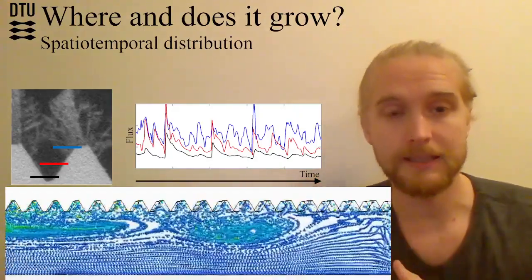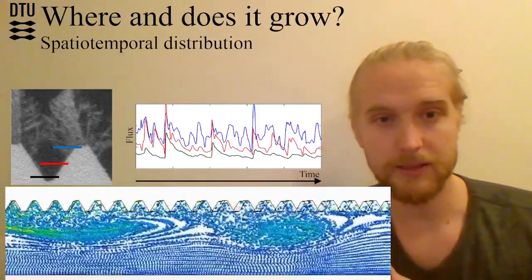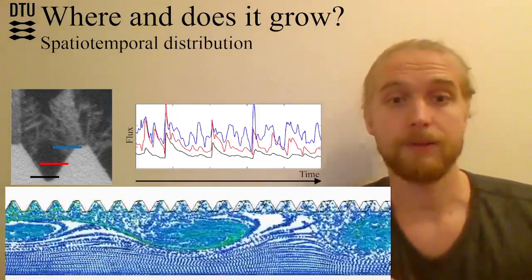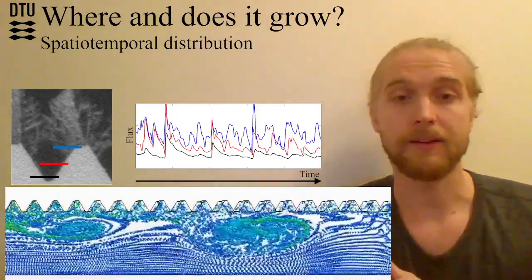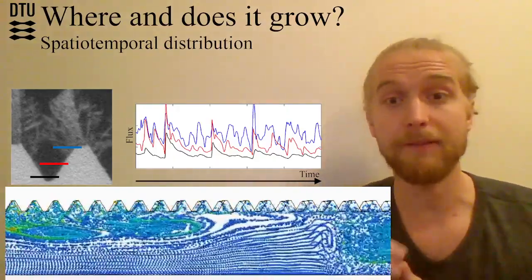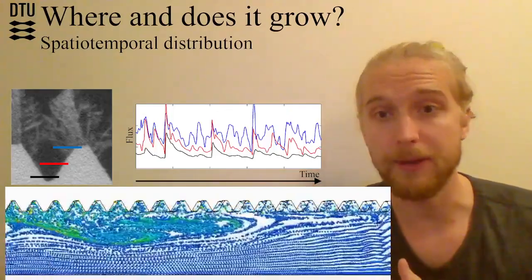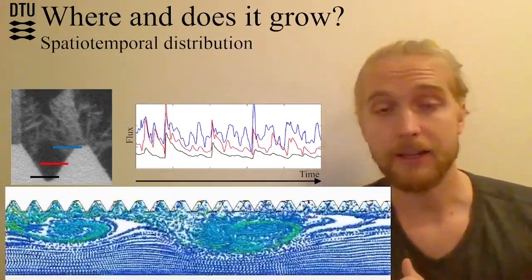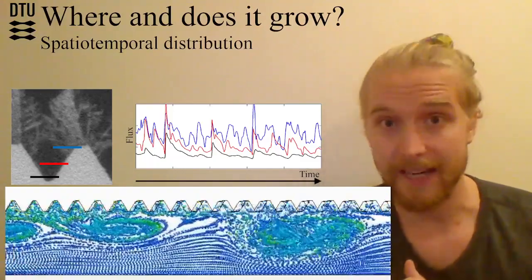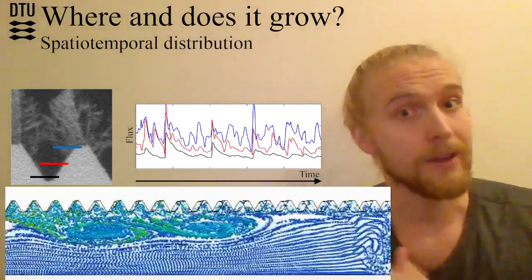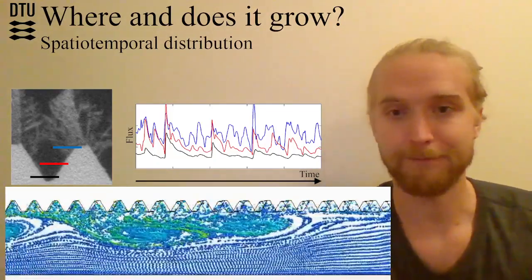And what you see is that there is a big periodicity shared between the blue, red, and black line, while the blue and red line, which represent the top and middle part of the threading, have some lower frequencies that are lost down at the bottom. And this indicates that a higher degree of mixing and also more reaction is taking place on the top of the threadings, indicating why more scale is forming there.